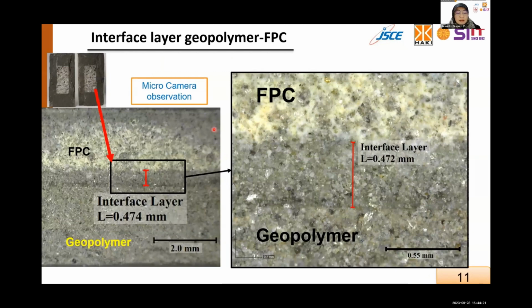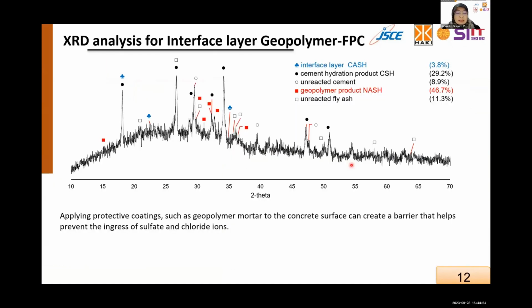And as geopolymer is attached very well to the FPC concrete, it creates a very thin but strong layer between these materials. This is the FPC, and this is the geopolymer. We found that the interface layer is very thin, less than 1 millimeter. By using micro camera observations, we see that it seems like the geopolymer penetrates the surface of the FPC and then creates another mineral. And this is what we found.